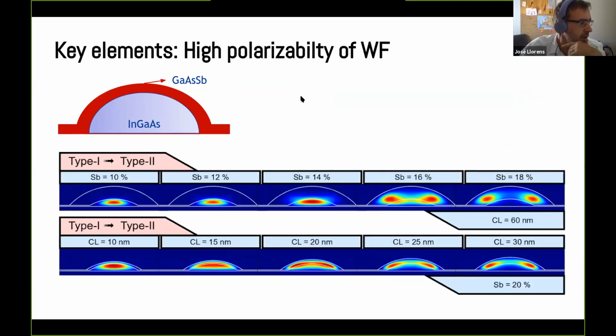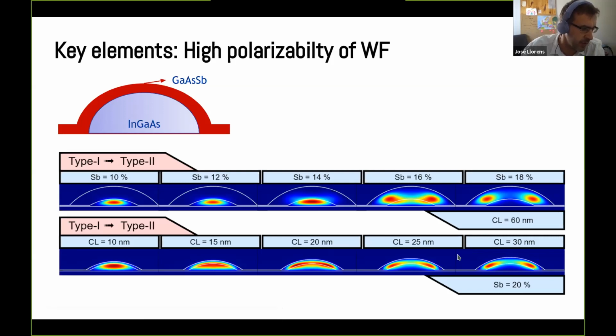So the two key elements are, on the one hand, a highly polarizable wave function. For that, we used indium gallium arsenide quantum dots covered by an overlayer of gallium arsenide and antimony. By changing, for example, the amount of antimony, we can change from type 1 confinement to type 2, meaning that the electron, instead of being confined inside the nanostructure, is expelled out and is confined in the overlayer. This is what we refer to as type 2, while this other type of confinement is type 1. And it's also possible, being in the type 2 confinement, so for a high antimony concentration, to reduce the thickness of this overlayer, and we are effectively pulling down the whole wave function towards the nanostructure.